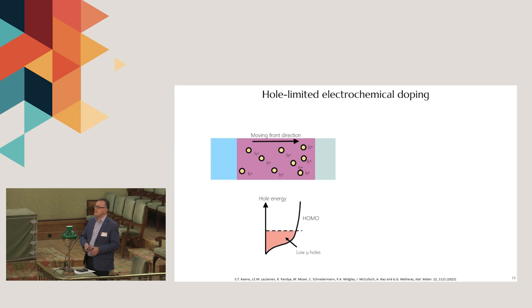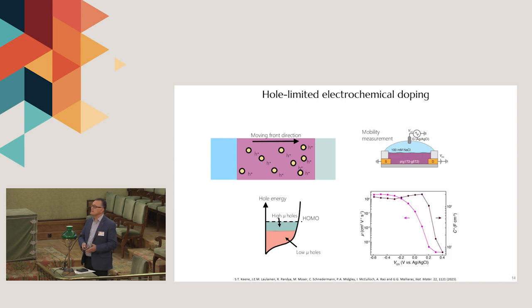As you fill up the low-lying states in the highest occupied molecular orbital, the one where holes are transported, you end up having a change in the mobility. And you go into a regime where a high density of states allows the holes to move faster than ions. This is supported by measurements of hole mobility in organic transistors that show the hole mobility to undergo massive changes in magnitude upon doping. There are other interesting phenomena.